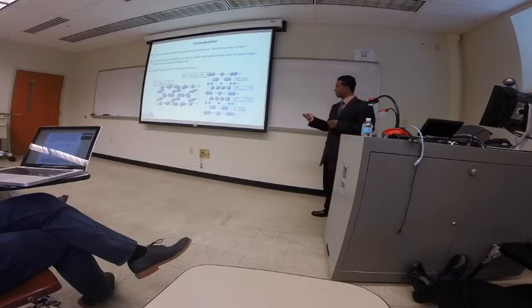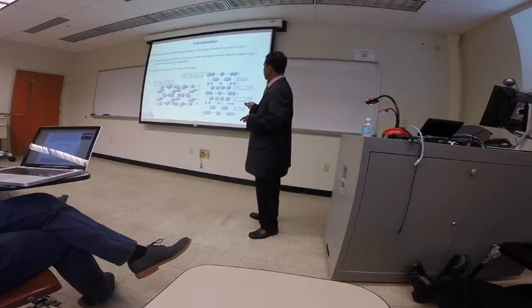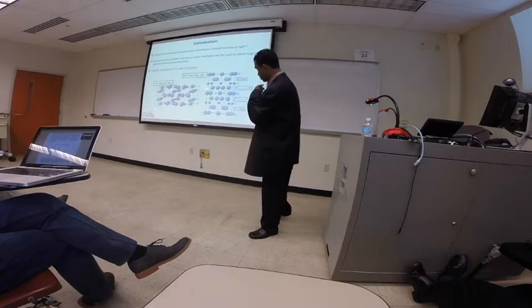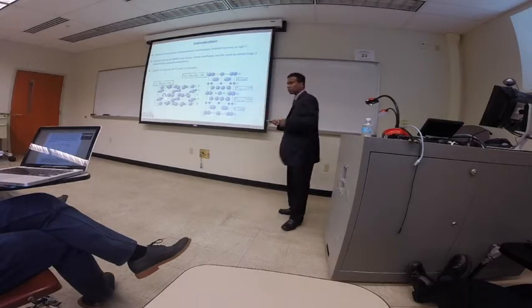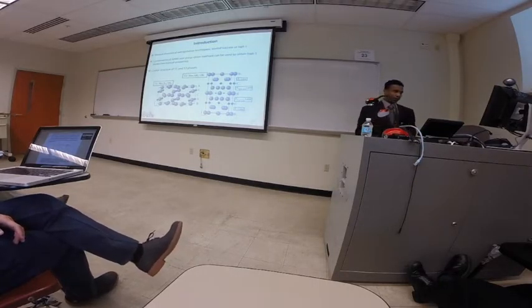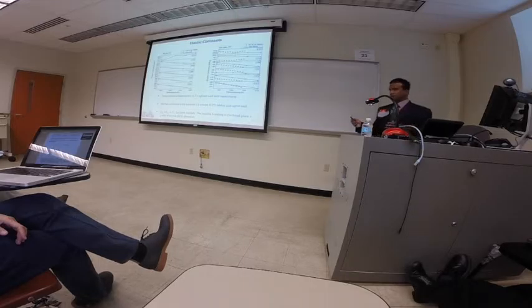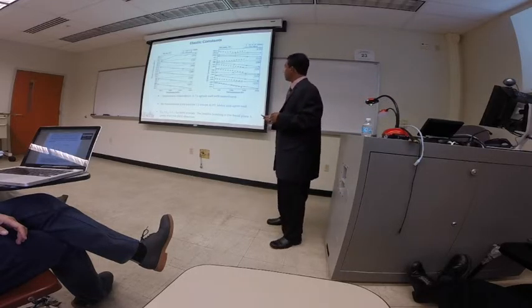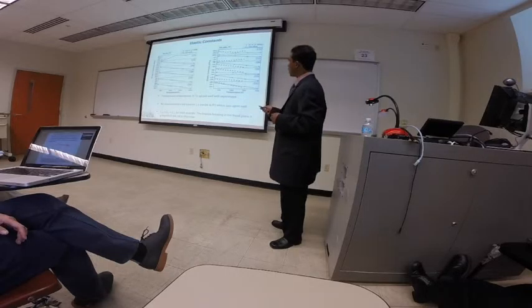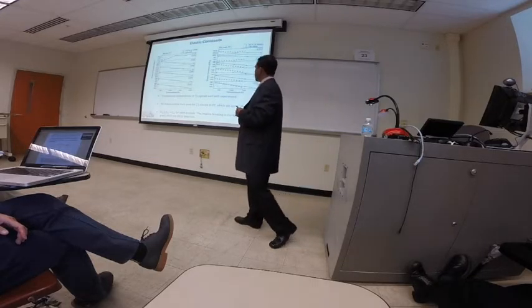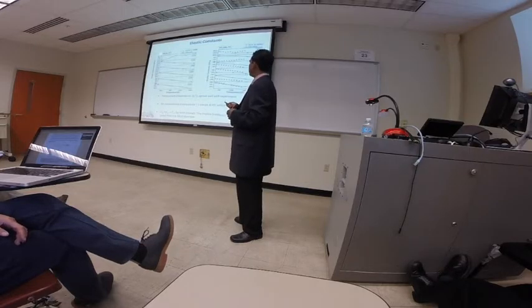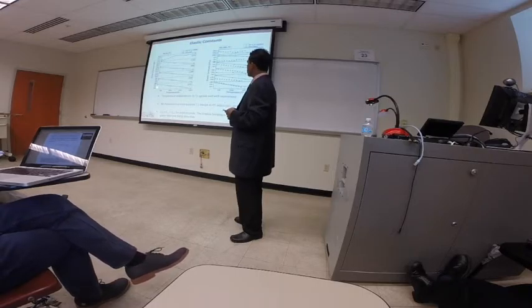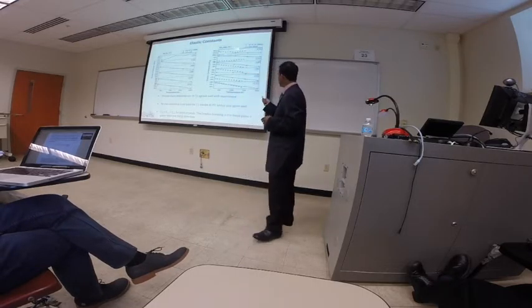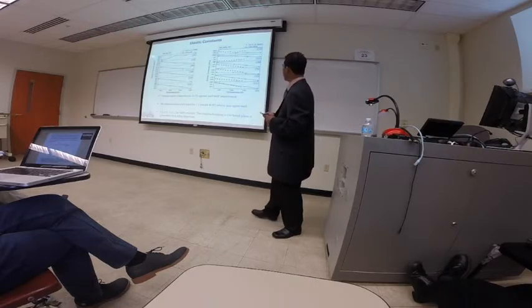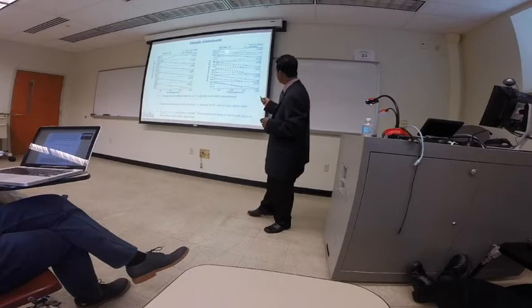So to give you a brief introduction about the two crystalline phases, T1 and T2 phases have D8m and D8l crystal structure with AB stacking, with molybdenum silicon elements. I'm not going to talk about the details of the method, but just give results. This is a comparison of our calculated values against the experimentally found results given by these red dots. For T1 phase, we could only find room temperature measurements, which are close to our results. But for T2 phase, there was a study done up to 1500 Celsius, and the Cij values relate closely to the experimentally found values.